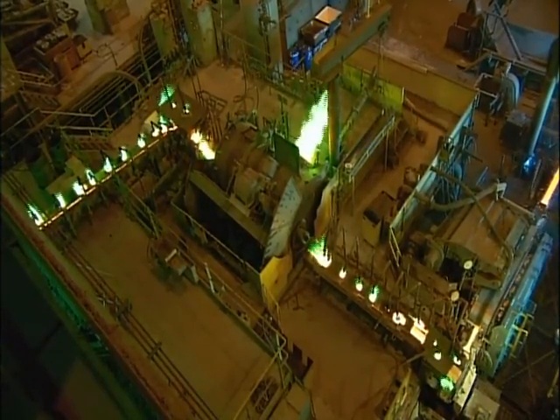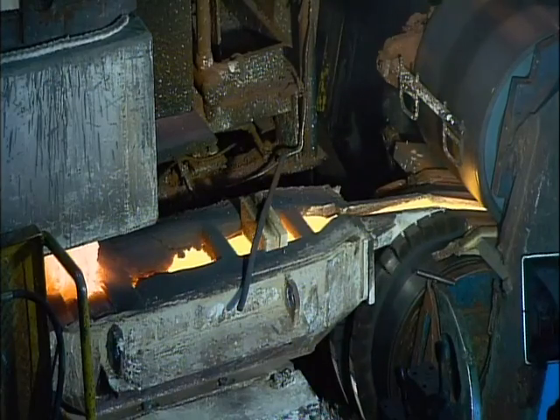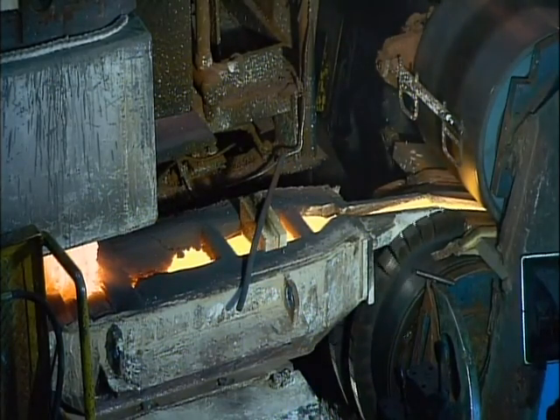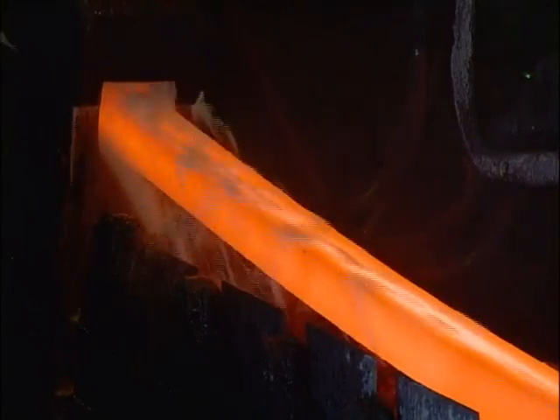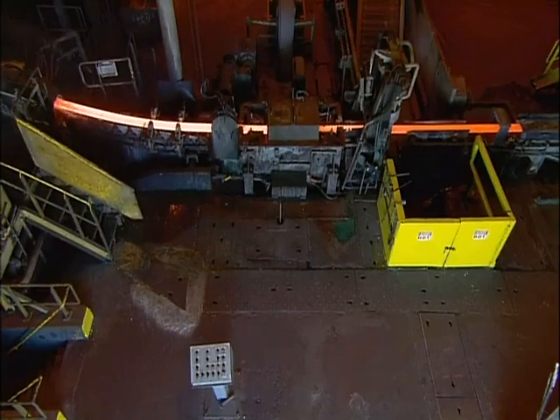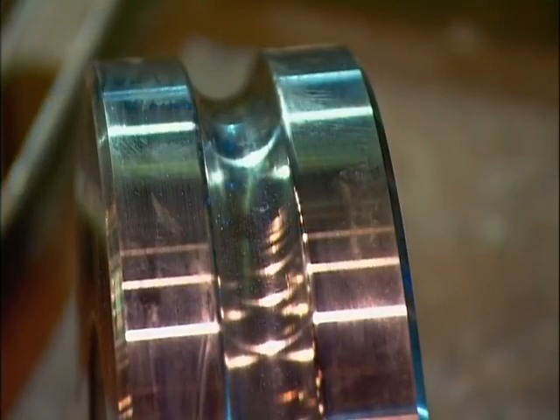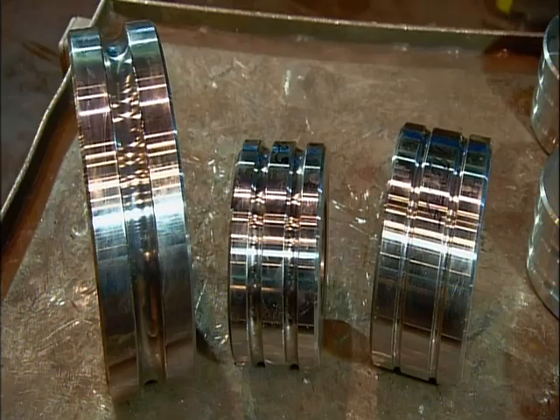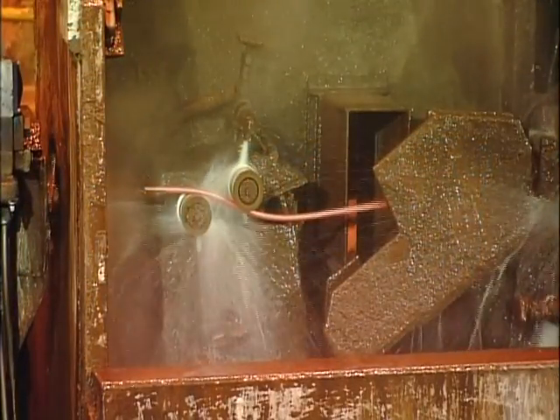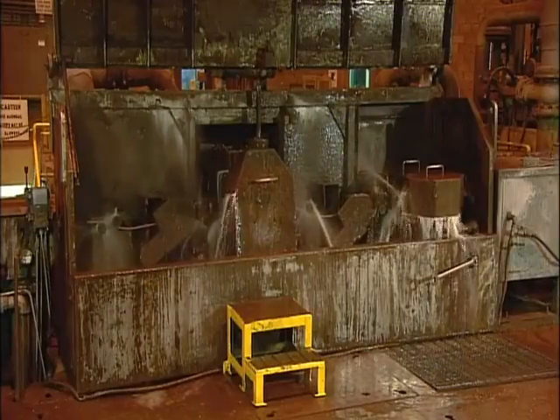They also process pure copper into rods, a form more suitable for manufacturing electrical wiring. Molten copper moves through an opening in a mold and, cooled by water, forms a continuous rectangular bar. Grooved rollers then take it from rectangular to round, reducing the diameter substantially. As the copper travels through the grooves, it becomes an eight millimeter thick copper rod.